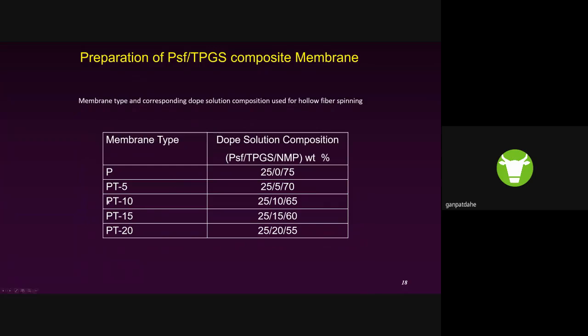So here what we did is create five different compositions to make this hollow fiber membrane. The first one, P, is nothing but a pure polymer system where there are no additives. It consists of 25% polysulfone and 75% N-methyl pyrrolidone. Similarly, PT5 has 5% vitamin E TPGS, PT10 has 10%, PT15 has 15%, and PT20 has 20%. We kept the polysulfone composition the same and just varied the TPGS composition.